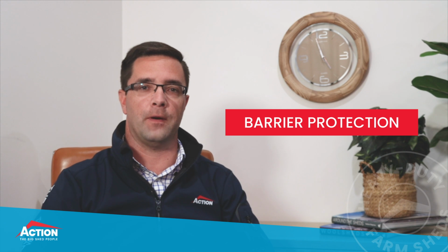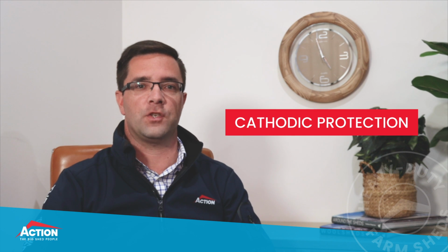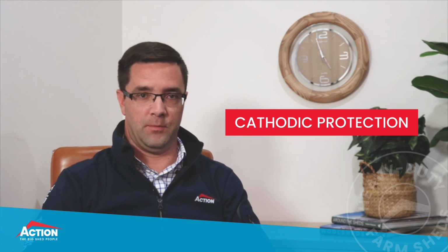So, how does hot dip galvanizing actually work as a protective coating? Well, we can break this down into 3 points. Number 1 is barrier protection. Because zinc is so dense, it is very hard for anything to penetrate it. Number 2 is what's known as cathodic protection. Zinc corrodes preferentially to steel, but at a much slower rate, so that even if the zinc coating is damaged on your steelwork, the zinc in the area will still protect the steel from corrosion. That's what's sometimes referred to as a sacrificial coating.